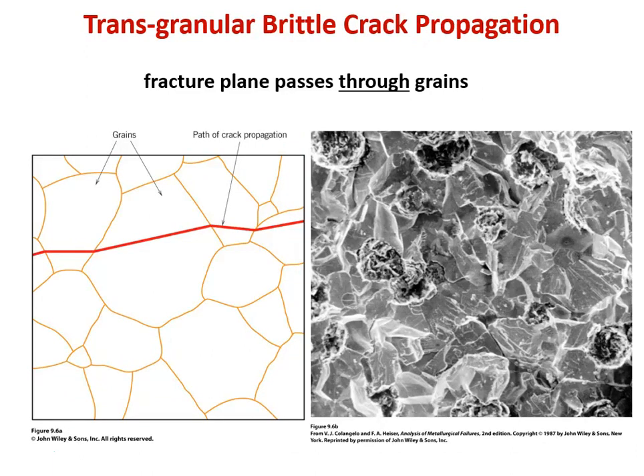Okay, getting further into types of brittle fracture. If we have a multi-grain material, like a polycrystalline metal or a ceramic, but mostly we'll be discussing metals because we're pretty sure that ceramics are brittle. So thinking about a polycrystalline material, if you have a crack propagating in a brittle manner, very little deformation going on, it can either go through grains or it can go around grains on the grain boundaries. So if the crack passes straight through the middle of grains, we call this transgranular brittle crack propagation. If it goes along the grain boundaries, we call that intergranular.